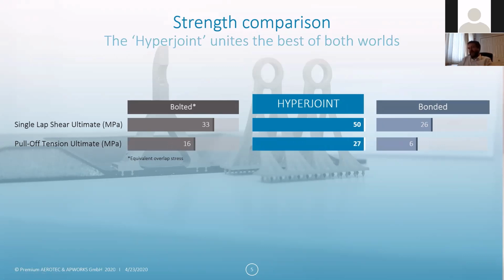And when we talk about thicknesses of laminates in the range where this is applicable, which is ideally in the range of, say, 3 to 7 millimeters, that's quite competitive compared to a bolted joint, so a higher ultimate strength than a bolted joint, and also higher than a bonded joint in pure shear. If we talk about pure tension, so pull off, trying to basically pull it out of the laminate, it's quite substantially stronger. And the main reason is that you've got so many local areas that are really gripping deep into the laminate. And so you're generating a lot more resistance to failure than with a single fastener head, or in the case of a bonded joint, generally you just remove the first ply. If you've got a good bond, you just take the first ply, the first thin layer of carbon off the rest. So that's, of course, a big advantage.